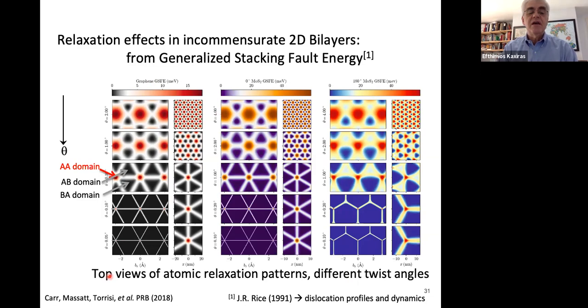So what you see here are top views of the atomic relaxation patterns at different twist angles. As you go down the column, the twist angle becomes smaller and smaller. It's 2 degrees here, 1 degree, half a degree, and so on. And this is graphene, and the other two columns are for molybdenum disulfide. And there are two subcolumns in each case. So this one is for configuration space. This is for real space relaxation. So let's look at the real space relaxation because it's a little bit easier to interpret.